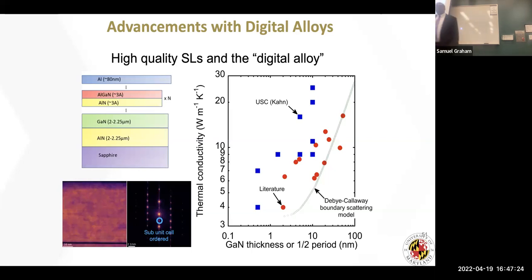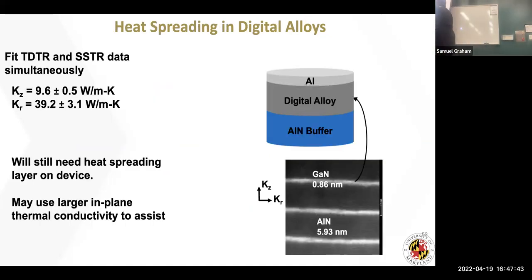Remember before I showed you that when I made these AlGaN structures, the thermal conductivity was below 10. You can see when we start doing these digital alloys, and this is just the first round of tests that we're doing, we're pushing the thermal conductivity up. But not only are you pushing the thermal conductivity up through the thickness, what's also really interesting, and this is another picture right here, is that we get high anisotropy, where we get heat spreading within the plane. This is a measurement on one that we recently did where the kz through the thickness was 9.6, but within the plane, this way, it was close to 40.